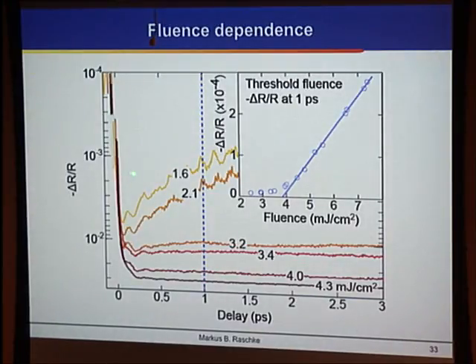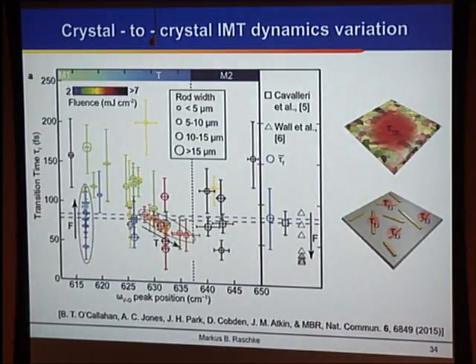And so when we study the time it takes for this transition to happen and vary a number of parameters, whether we are in which of the intrinsic phases, we can look at the dimensions of the crystallites, we can vary the fluence, then you see that you get a large variation in this dynamics. This is too much to describe in detail, other than that you see a lot of scatter. But if you take the average of this, then you get very good agreement with what people measured in polycrystalline thin films.